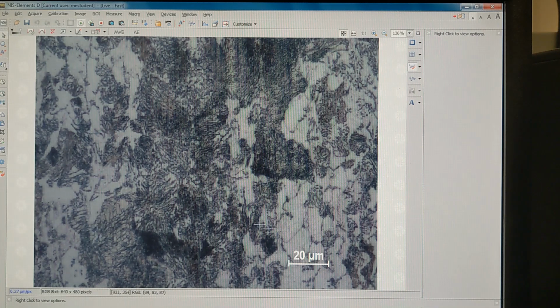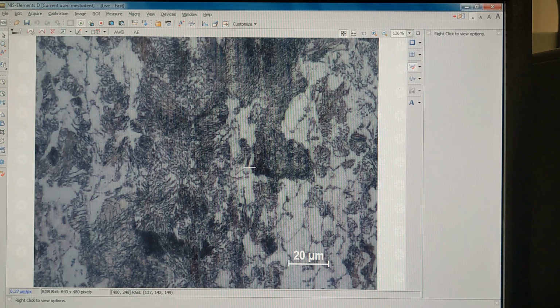So here you can see we have individual ferrite grains. These little guys here are our grain boundaries for ferrite. You see they're about, I don't know, 10, 15 microns. And we have lots of pearlite, lots of this layered structure, kind of this whole central column. It appears is some form of pearlite.